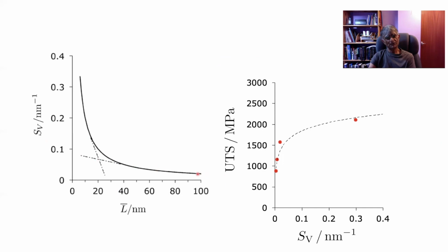Now, notice that at first, the amount of surface per unit volume doesn't change very rapidly, but around 20 nanometers, it starts to rise sharply. Okay? And this trend is also reflected in mechanical properties. So here, if you look, 20 nanometers is around 0.1 in terms of surface per unit volume here. So if I look at the strength, any grain size smaller than 20 nanometers does lead to an increase in strength, but it's not as sharp an increase as when we go from a large grain size to about 20 nanometers. So let's define our nanostructure as something having a mean linear intercept that is of the order of 20 nanometers. If it is greater than 20 nanometers, then we expect to see sharp decreases in strength levels.